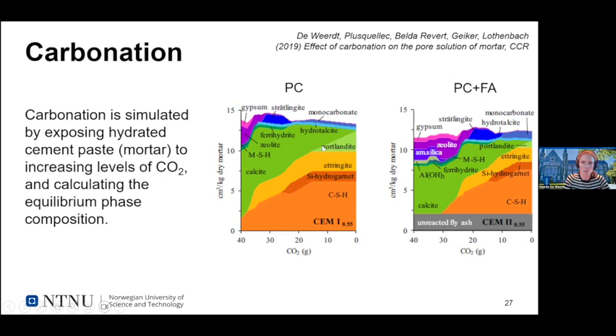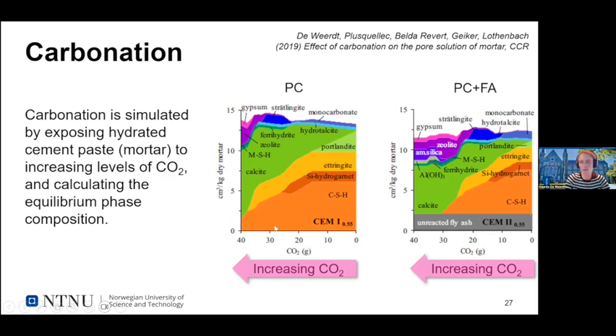What we did here is we simulated carbonation by exposing the hydrated paste or mortar to increasing levels of CO2. So we start with 0 grams CO2 and we increase the level of CO2 our cement paste or mortar is being exposed to. And we calculate the equilibrium phase composition upon exposure to this CO2. If you focus on the Portland cement, the first thing that happens upon carbonation is that your Portlandite is predicted to decompose and form more calcite, the darker green phase.